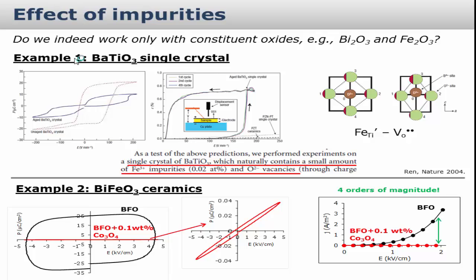and that's basically related to switching of the domain walls by application of the field, and then these domain walls will somehow be pulled back to the initial configuration with zero strain, because of some defect complexes that are present inside the material. In this case, this is an acceptor site in a pair with an oxygen vacancy. They claim in this paper, and this is quite general, that iron is present as an impurity in nominally undoped barium titanate at very low concentrations, and you can see how an impurity can have a huge influence on how the material behaves in terms of macroscopic properties.